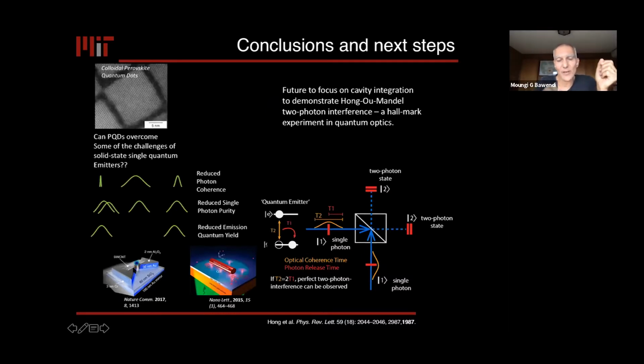And so there are ways to make T1 faster, for instance, by putting the material into a cavity where we can change the density of states for photons, for light, to make it overlap with the photons that want to come out of the particle. Putting them in a cavity, that's called the Purcell effect.